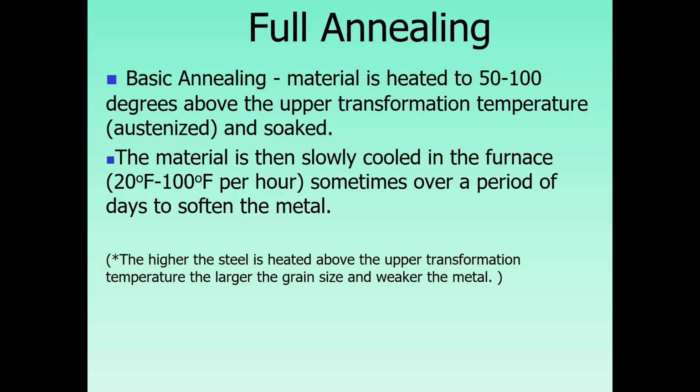Full annealing. Full anneal cooling is usually performed in the furnace at a prescribed rate. The resulting microstructure is a coarse pearlite ferrite mixture. Machinists will usually appreciate machining the annealed material due to its pearlite microstructure. This material has a relative softness and great chip-breaking properties compared with tempered martensite microstructure.